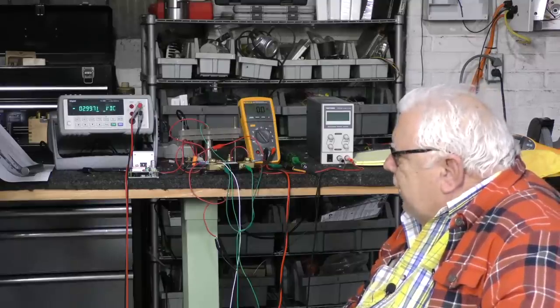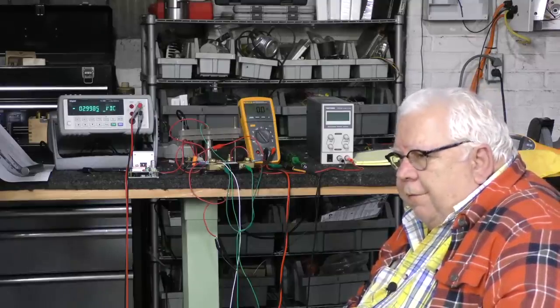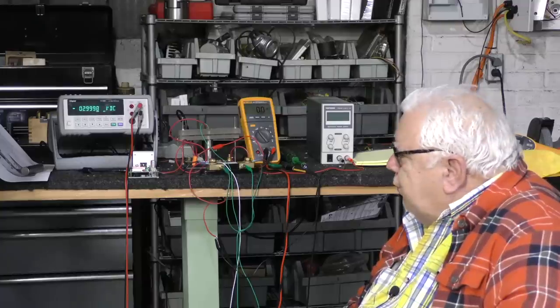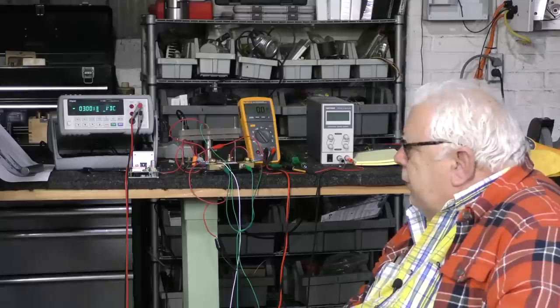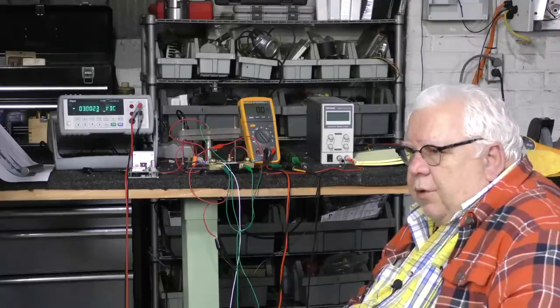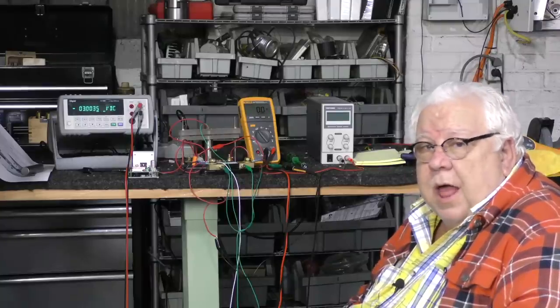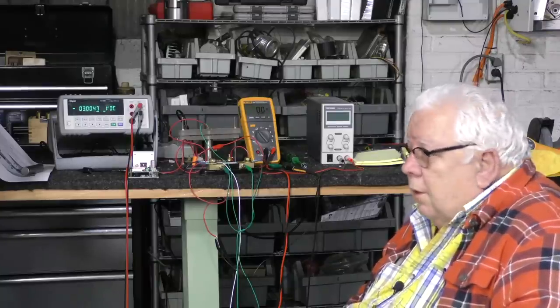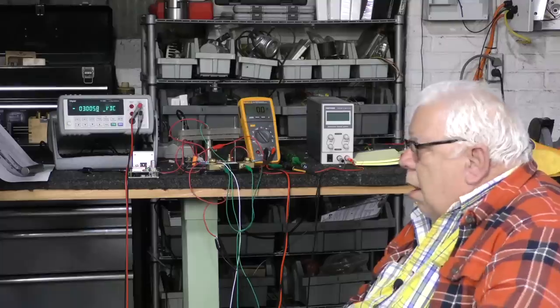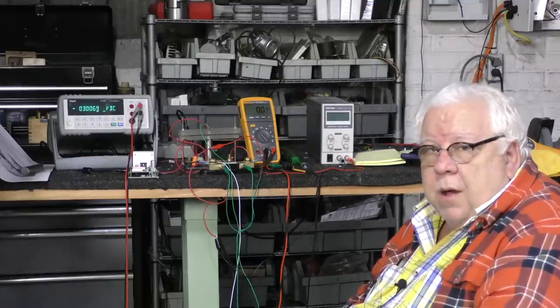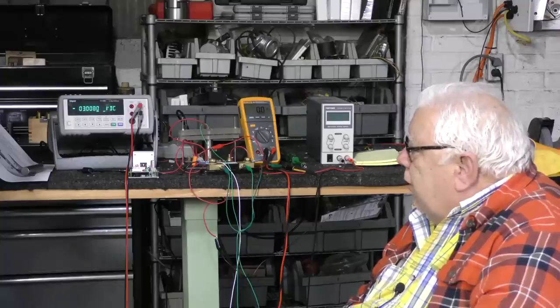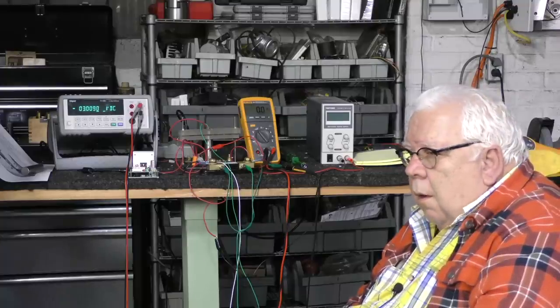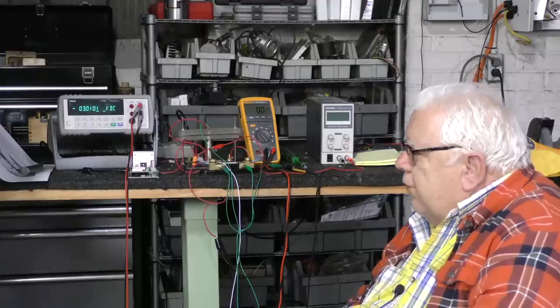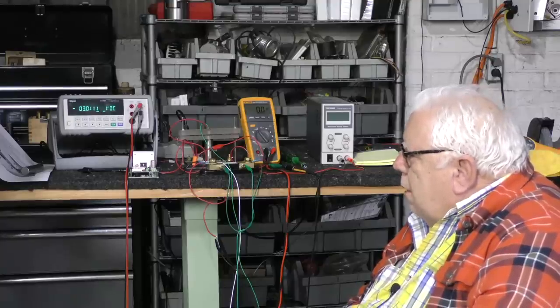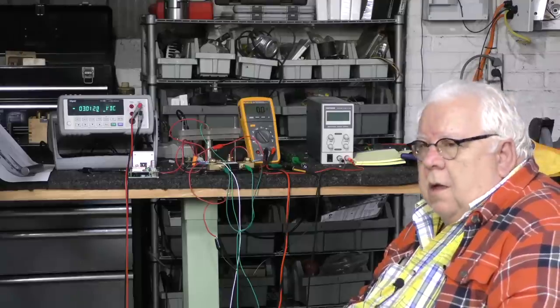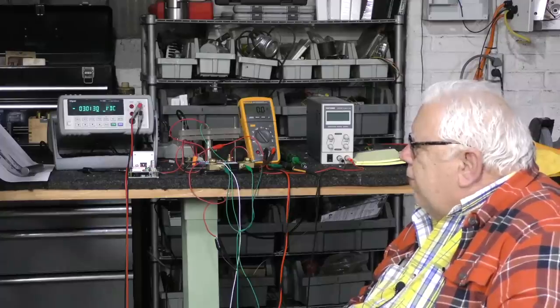And my best guess here, and again, this is kind of squishy, it depends on what you count and how you do the test. They've got 5 amp hours. They must have been doing it at 0.1C, and you're not going to get that on the road. So, figuring 70 miles an hour, a 4-hour drive, you're not going to get 310 miles either at 70 miles an hour. So, I think that's a pretty good figure at 70 miles an hour for 4 hours, and we didn't make it 4 hours, about 3.5, give or take.